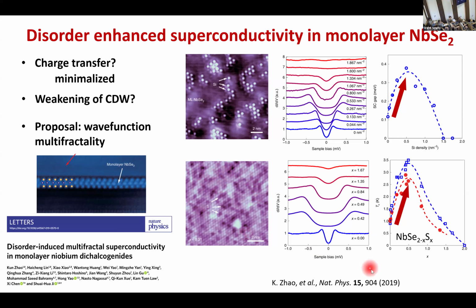So when they grow this thing with a mixture of selenium and sulfur, they see that the TC of the sample goes up first and then goes down. So this is kind of interesting. And then they claim the idea of why this happens is what they call multifractality, which is somehow related to some complex physics dynamics.